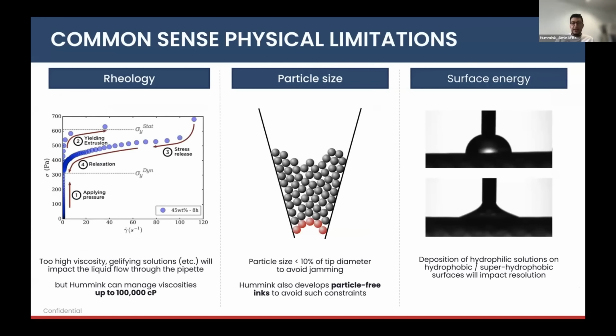As for the limitations that we have, trying to anticipate that question a little bit, they are mostly on the ink. The rheology, you have to consider that, even though we can go up to 100,000 centipoise. Particle size, if you have any, to prevent clogging of the pipette, but we respect the 10% ratio between particle size and the line that we deposit. We also manufacture our own ink to meet the requirements of the technology. And obviously, since it's a capillary-based technology, surface energy is very important. So surface tension, contact angle of your substrate. And we know how to adjust these three elements to be able to make the ink that works with your application.